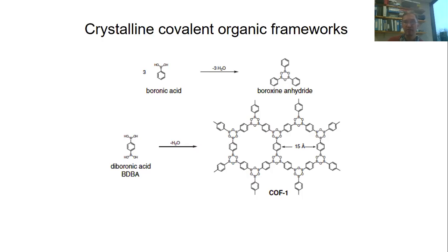However, and that is very important, the polycondensation that occurs here still has to occur in a reversible manner in order to avoid the formation of kinetically controlled products. Imagine that, for instance, this carbon bond, which is a single bond shown here, is allowed to freely rotate. Therefore, this group, at a particular point in time before it's fully condensed, or we can also look at this one here, can actually move out of plane.